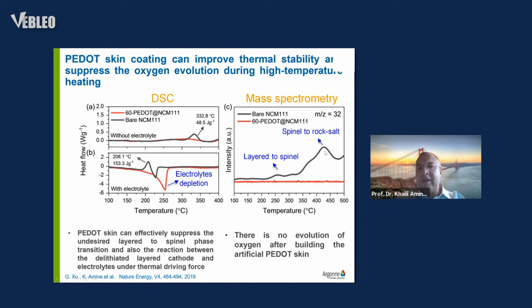And then when you go higher in temperature, you have even more oxygen release that leads to the spinel to rock salt transition. So you know that when you have oxygen release, it will react exothermically with the electrolyte and create significant thermal hazard. As you can see, when we add electrolyte to the charged cathode, we have a very significant reaction that happens at very low temperature. While with protected material, we did not see any exothermic reaction. We have an endothermic reaction, or electrolyte depletion, if you want, because of evaporation.